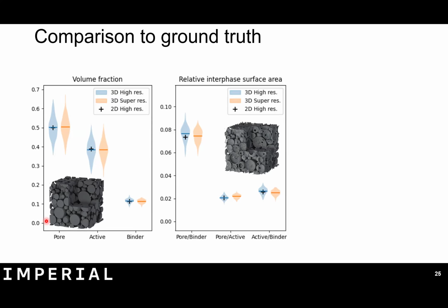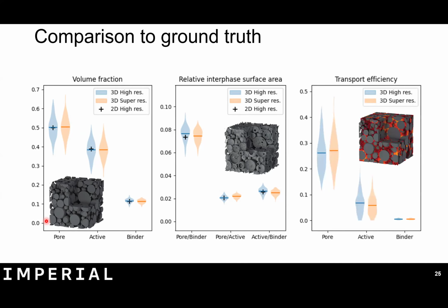So we can show that both in terms of the mean and the distribution statistics, it is very similar to the ground truth for things like volume fraction and surface area. But more excitingly, it's very similar to the ground truth for more elaborate metrics like transport simulation results, like tortuosity factor. And so what's nice about this example is, in the data fusion sense, tortuosity factor was not calculable from either the 2D input or the 3D low res input, because the 3D low res was actually missing one of the phases. So you can't get it from either of the training sets independently, but you could extract it really well from the combination.